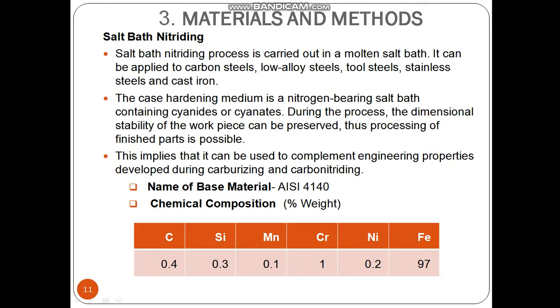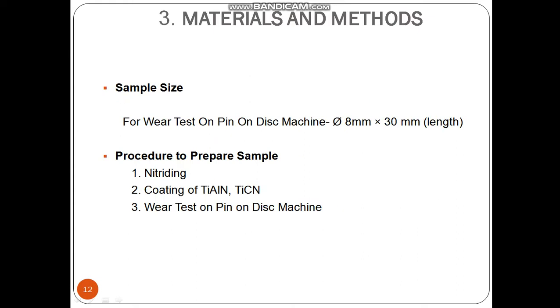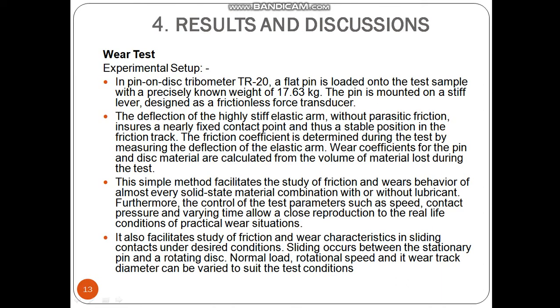Name of the material: AISI 4140. Chemical composition, that is percentage by weight: carbon 0.4, silicon 0.3, manganese 0.1, chromium 1, nickel 0.2, iron 97. Sample size for wear test on pin on disc machine: diameter 8 mm by 30 mm length. Procedure to prepare sample: first nitriding, then coating of TiAlN, TiCN, then wear test on pin on disc machine.